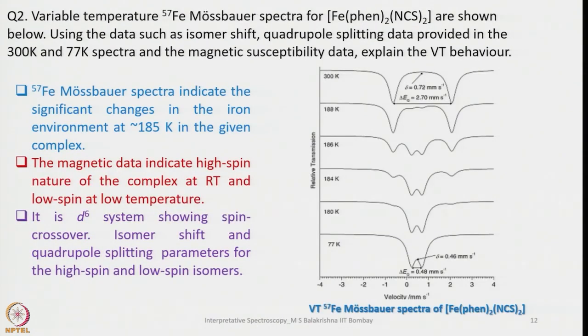There is one more question here. Variable temperature 57Fe Mössbauer spectra of this complex are given here, with two NCS thiocyanate and two phenanthroline bidentate ligands. Iron is in octahedral geometry, as shown below. Here it is shown, variable temperature starting from 77 K to 300 K. Using the data such as isomer shift, quadrupole splitting data provided in the 300 K and 77 K spectra, and the magnetic susceptibility data, explain the variable temperature behavior. That is the question.